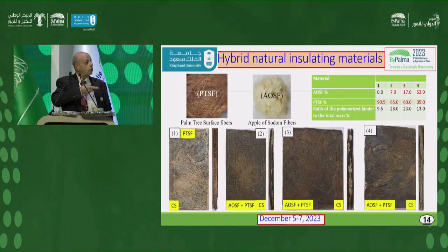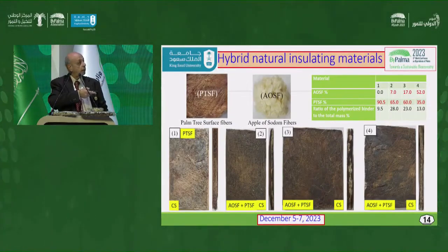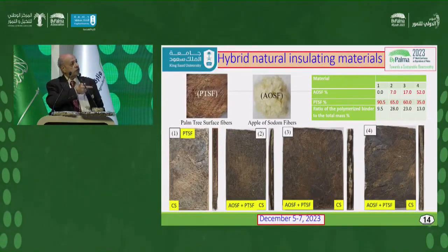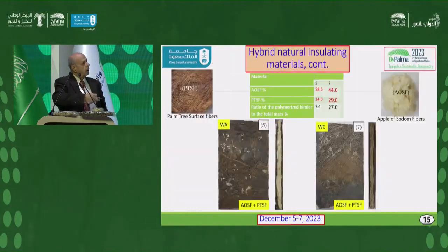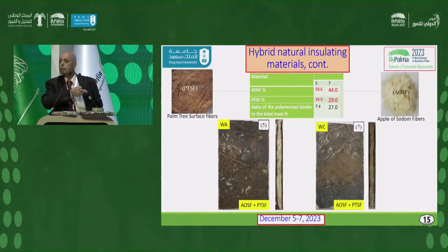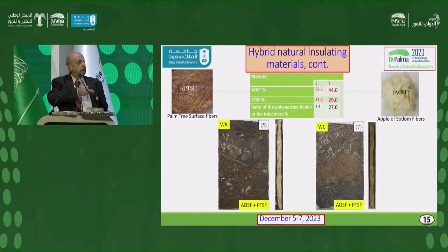The first one is pure palm tree surface fiber. This one is a different percentage, and all of them are using cornstarch as a binder. This is the apple of sodom fiber, and this one is the palm tree. So this hybrid is between these two with different compositions according to this table. These are another two samples, samples 5 and 7, which we use just for comparison. For this sample we use adhesive as another binder, and here we use white cement as another binder, just for comparison between different binders and their effect on the thermal conductivity.